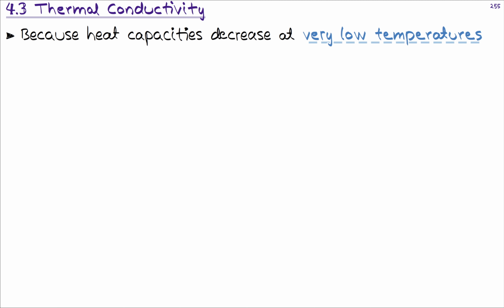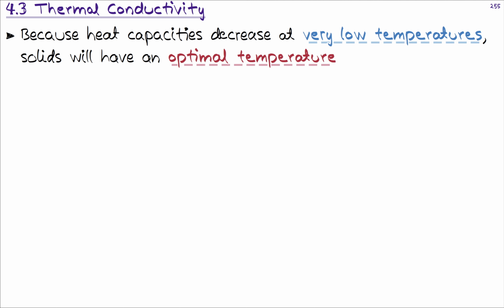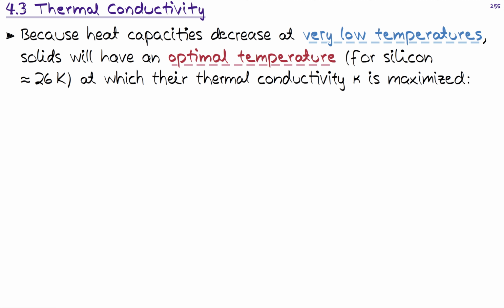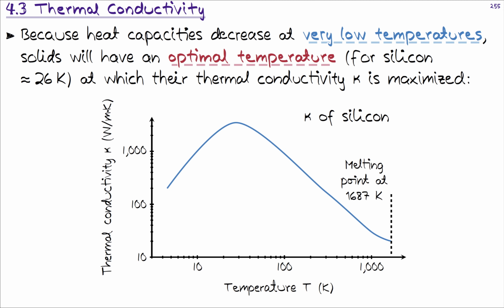And because the heat capacities decrease at very low temperatures, please recall the Debye model and our previous lecture on heat capacities of solids, that when we go to very low temperatures, we really have the T^3 dependence. And this implies to us that solids will have an optimal temperature range. And for silicon, I think it was around 26 kelvins, where their thermal conductivity kappa is maximized. So I'm plotting here an example figure, and this is silicon. And here we see that it's maximized at a given temperature.